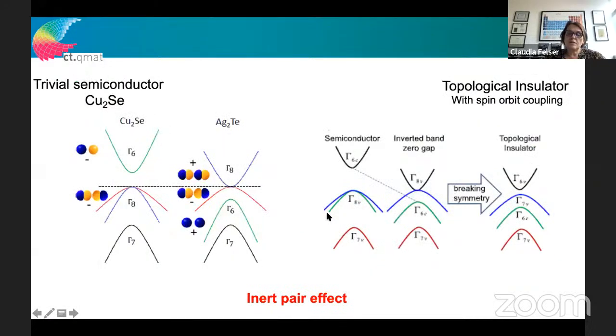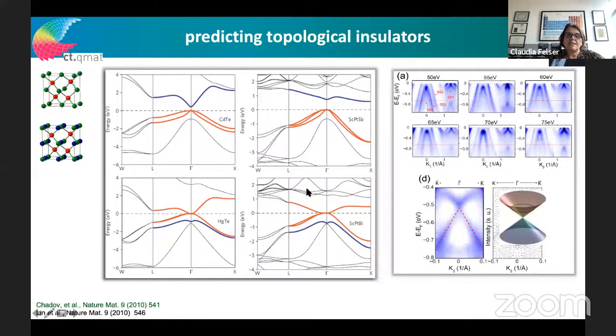But why are these ternary compounds interesting? I hope we make some progress here, because these compounds are also very often superconducting. If they have the band inversion, they are semiconducting, so no superconductivity, even if you dope it to the same electron carrier concentration like in the other case. So this one has superconducting and this one has non-superconducting behavior, which might be accidental - I don't think so.